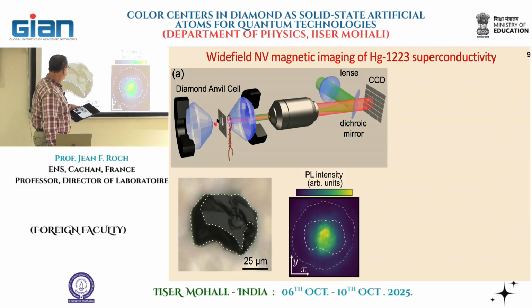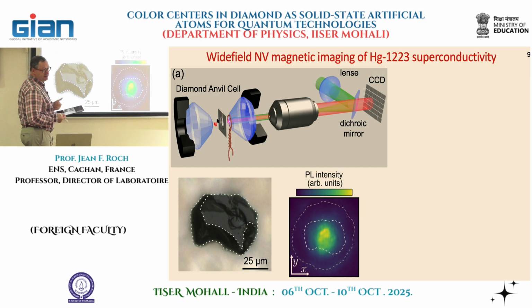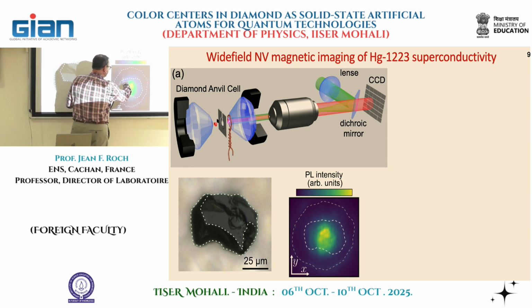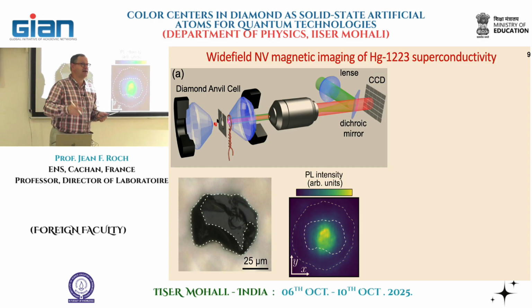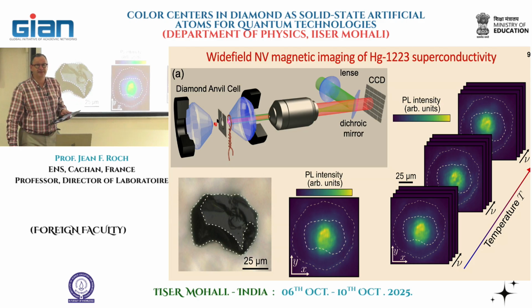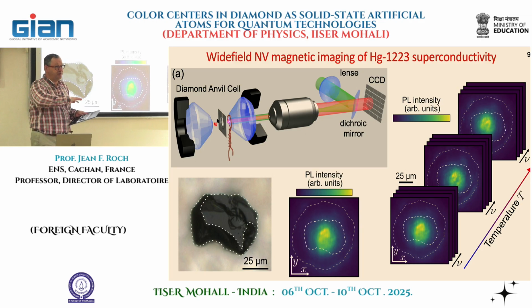So now we do the experiment. This is an image of the flake, which has some inhomogeneities that you can see here. And we integrate it here, so it's the scheme, and we study it, again, using wide field magnetometry. So you see the different steps, the different elements, as I showed you before. And this is now the PL intensity recorded over the sample. And we apply the same technique as I discussed. So we record at a given temperature, we scan the frequency. We record for each frequency the intensity map using the CCD camera. And then we simply change slowly the temperature. And we have all this set of information that we can now reanalyze afterwards.